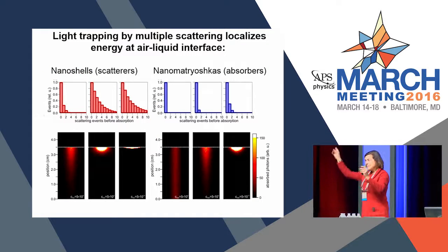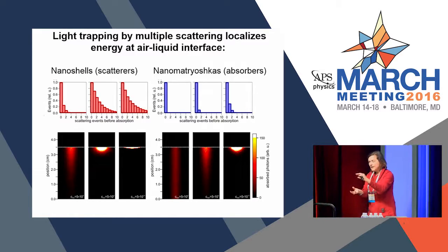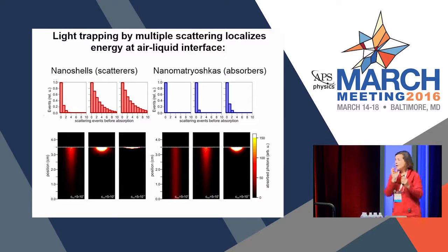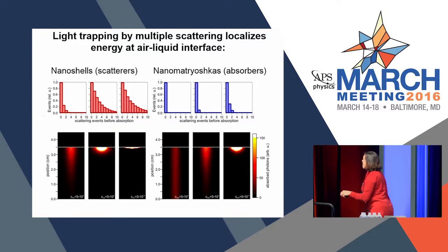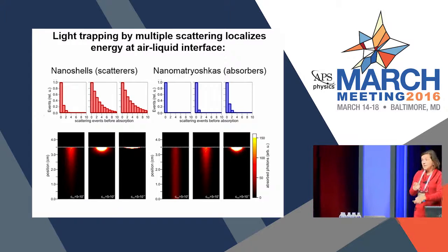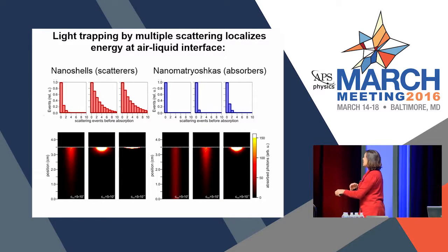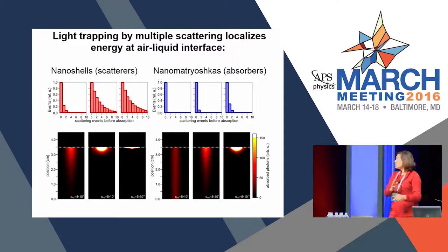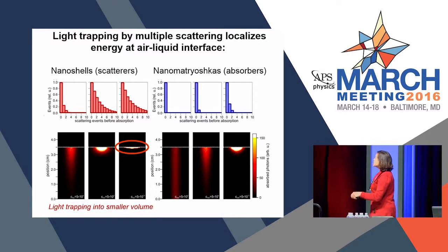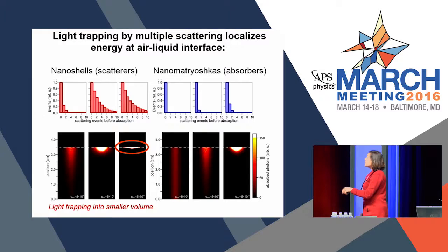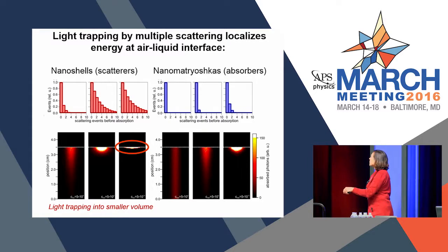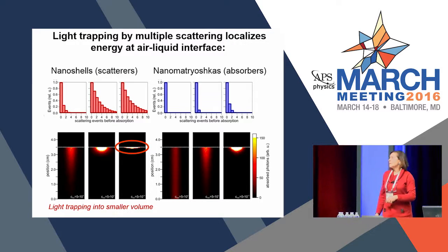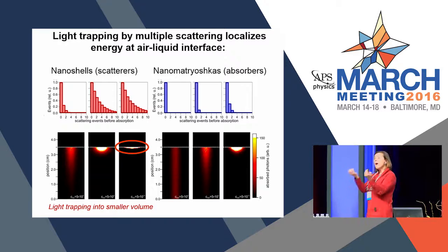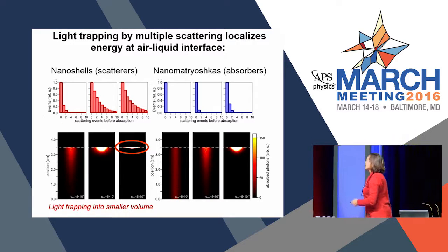Then if we look at the same experiment that I showed you before, a cuvette of fluid filled with nanoparticles, illuminated from above, what happens to the light energy as it gets absorbed? We change the concentration of the particles. For the scattering particles, we're increasing the concentration by 1 order of magnitude as we go from left to right, and an order of magnitude again, a factor of 10, a factor of 100, for the particles that are absorbers. What we find is that for high concentrations of the scattering particles, we have a tiny compressed volume of just a few microns where all the light energy gets absorbed, relative to when the particles only absorb light. So this is a light trapping effect, which keeps all the light energy in a narrow volume near the surface.